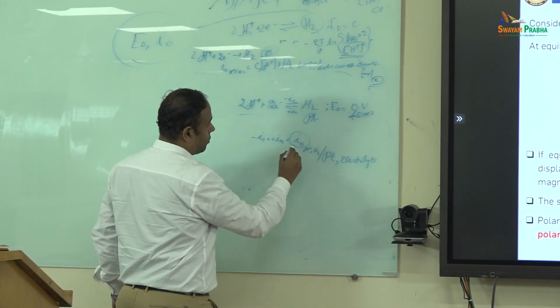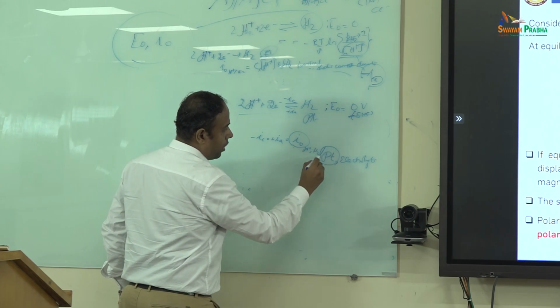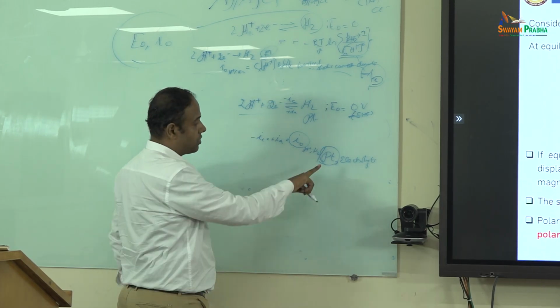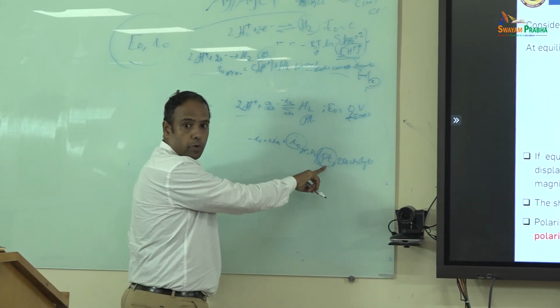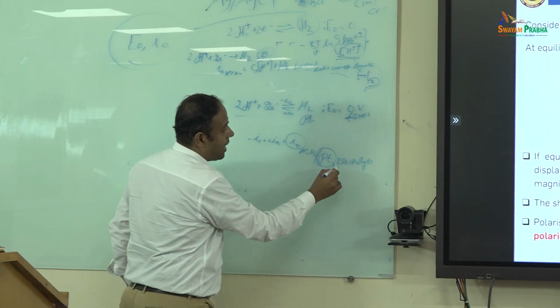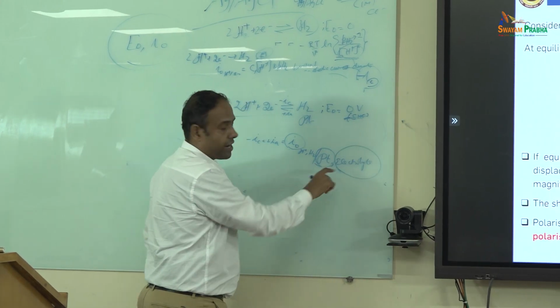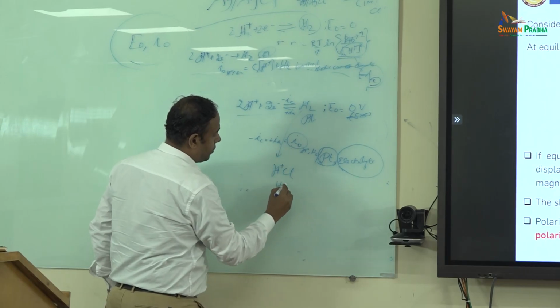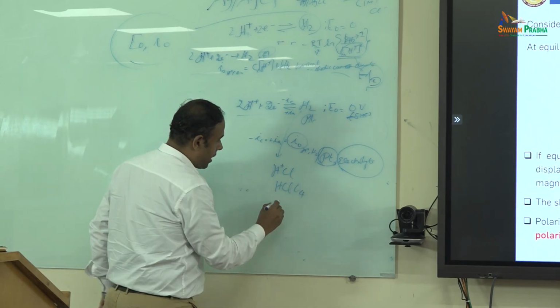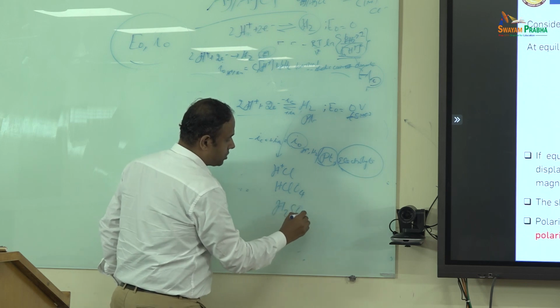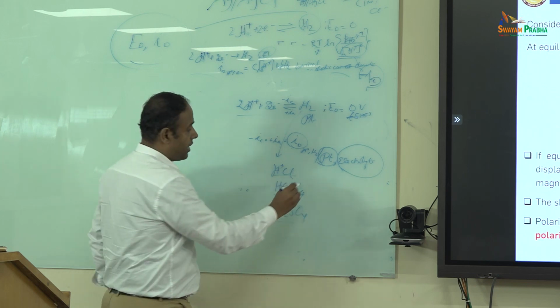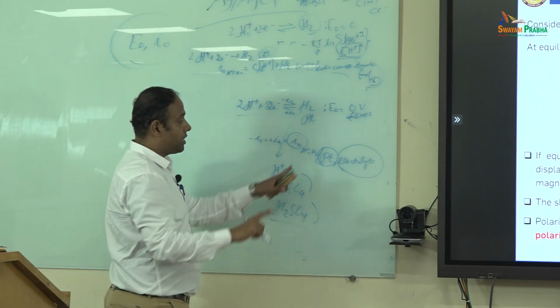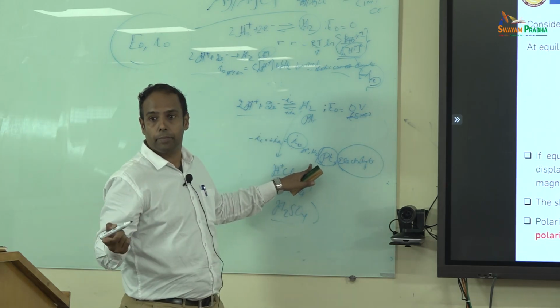So, this I naught value depends on what metal surface it reacts on, that is the electrode composition, the purity, the surface roughness, and also what electrolyte I use. I can produce this by using HCl, I can also produce this using HClO4, I can also produce this using H2SO4. So, for each electrolyte, your I naught on the same platinum surface will not be the same; it will vary.